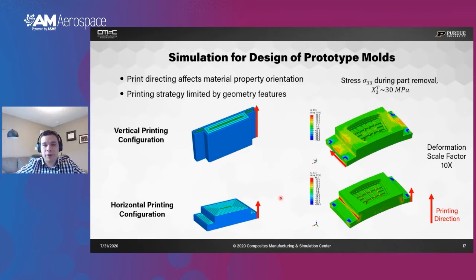So here, following the printing process, we perform a stress analysis, considering these two cases of print configuration. On the upper side, with the tool printed vertically, we can see that during the ejection process, we don't get significant stresses that can cause delamination. However, if we do the other printing configuration, we can have some stresses localized in this transition that can lead to delamination. Therefore, this was the choice for the print configuration.